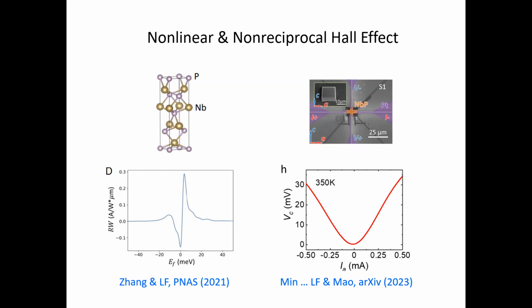And recently, experimental groups at Penn State University, Zhiqiang Mao, he actually fabricated the niobium phosphide device using a focused ion beam method. They create a very small crystal. Because this nonlinear Hall effect is driven by electric field, if you have a very thin crystal, you can get a large current density and therefore a large electric field. That's why this effect becomes pronounced. So now, in this material, the nonlinear Hall effect is observed at room temperature. And because the effect is so large, they can just measure direct DC transport, apply DC current and measure DC voltage.